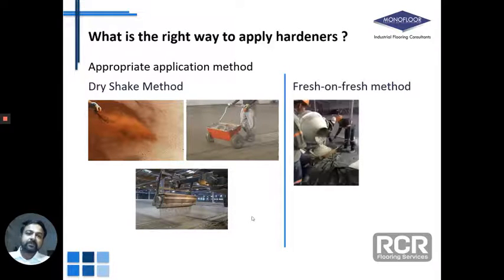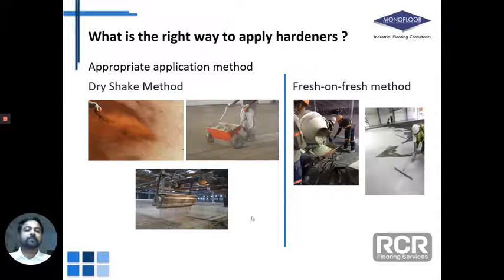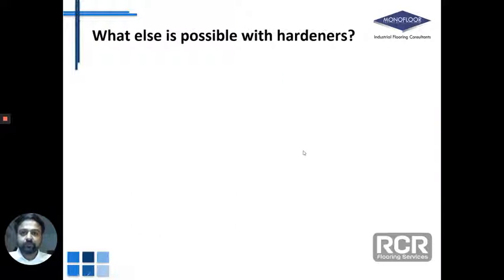The other method which enables a higher thickness of hardener layer to be used is, of course, the fresh on fresh method. There are certain hardeners that are manufactured tailor-made for such application methods. These hardeners are mixed as a slurry and applied on top of the fresh concrete. You follow it up with power troweling exactly the way you do for a dry shake hardener. But this is an alternate method for application of hardener, and you can go for a really thicker layer of hardener, or you can even increase the dosage, so to speak.